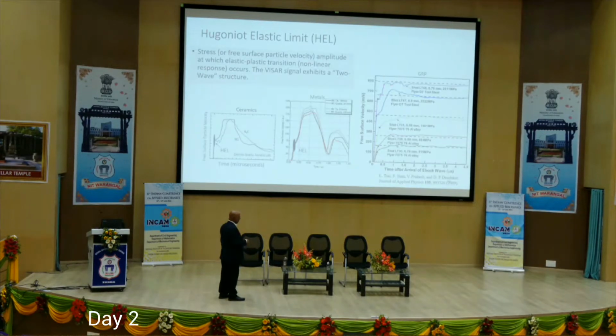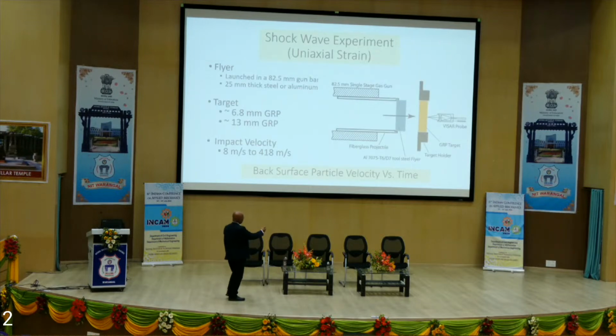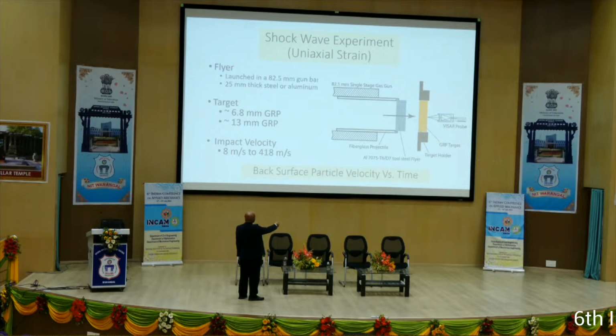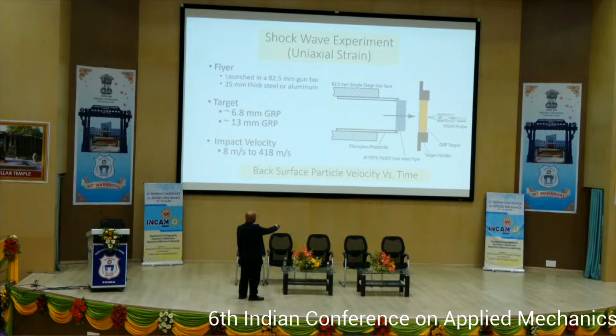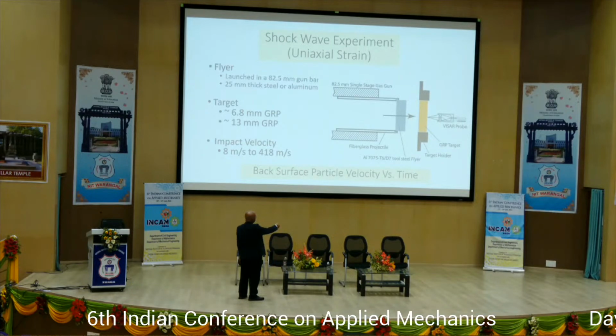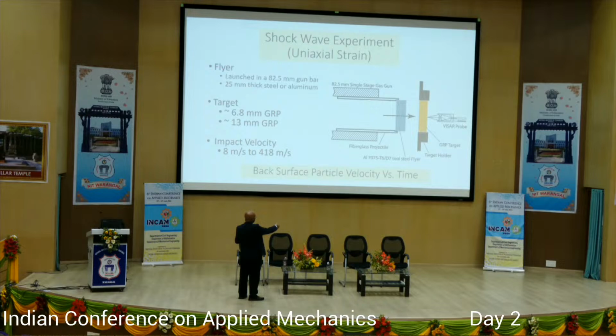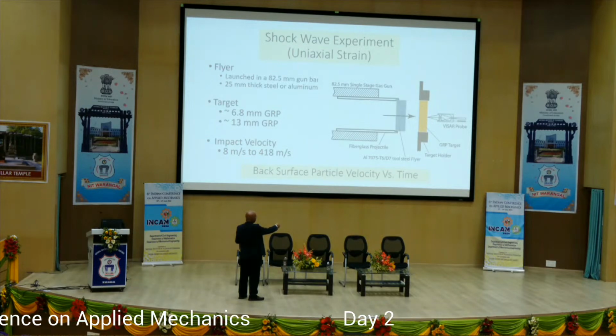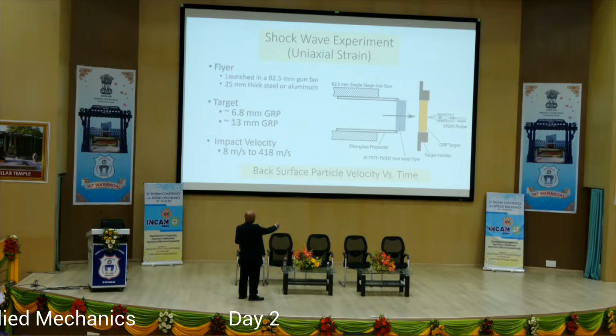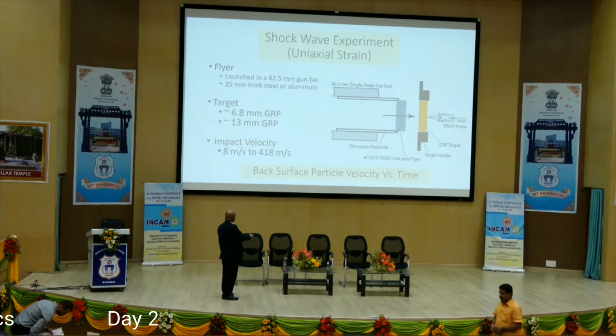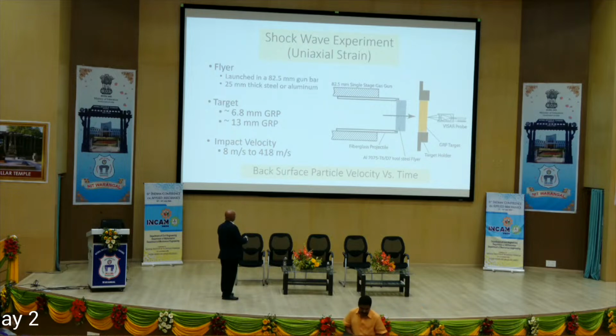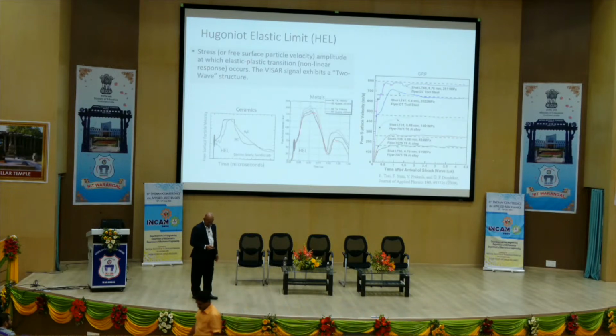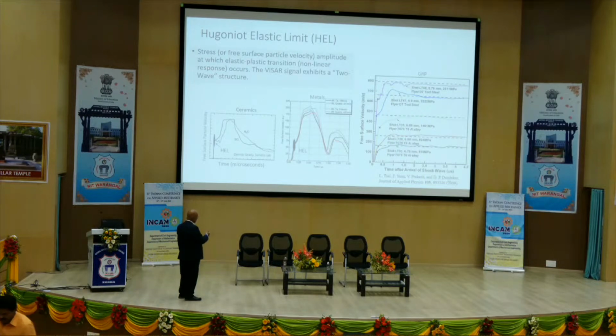You hit one plate on another plate, and then you measure the back surface velocity, the VISAR. That's a target, GRP, and that's a flyer, steel or aluminum. It hits, planar impact. All the material points move in one direction. All the other strains are zero. There is only one non-zero strain, which can be calculated from measuring the velocity versus time of the back surface. So the back surface particle velocity versus time becomes the data. So now you look at three graphs.